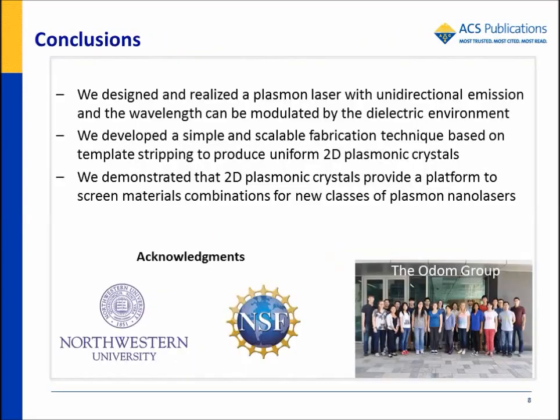To conclude, we designed and realized a plasmon laser with a unidirectional emission, and the wavelength can be modulated by the dielectric environment. We developed a simple and scalable fabrication technique based on template stripping to produce uniform 2D plasmonic crystals. We demonstrated that 2D plasmonic crystals provide a platform to screen material combinations for new classes of plasmon nanolasers.